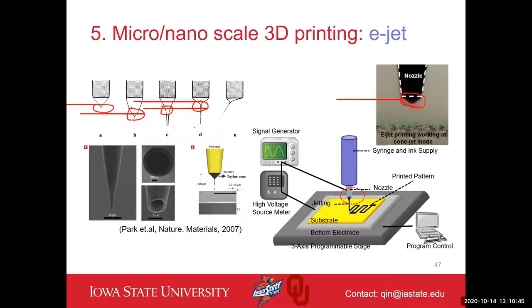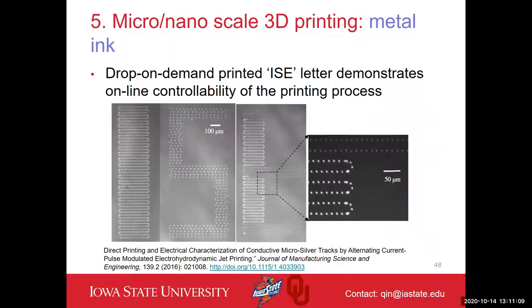Okay, that's how we can achieve printing in the micro nanoscale. The electrical force will only force a drip at the tip of the nozzle. That's how we reduce the dimension. For a nozzle with the size of 20 micrometers, it is possible to achieve a 3 or 4 micrometer droplet generation. Then we achieve micro nanoscale printing. The results that I had before show how precise the droplet can be. I can precisely print droplets with sizes between 3 to 5 micrometers. It can go as low as 500 nanometers as the diameter of the printed dots. This is the silver dots that I printed before.